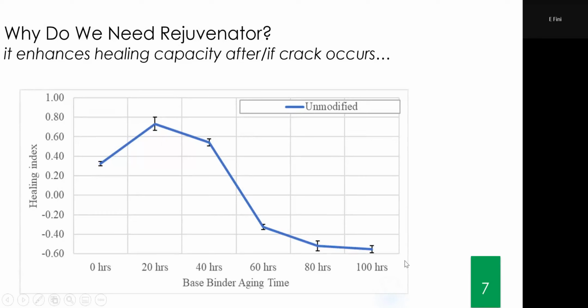There are ways to measure the healing capacity. And here you can see the healing is gone. After 80 hours or so, the material doesn't heal anymore because it cannot close the crack. You make the same damage and wait for the same amount of time as for other samples, but this one doesn't close the crack. So healing capacity is reduced as aging progresses, and at some point is almost gone. Let's see what the rejuvenator does.